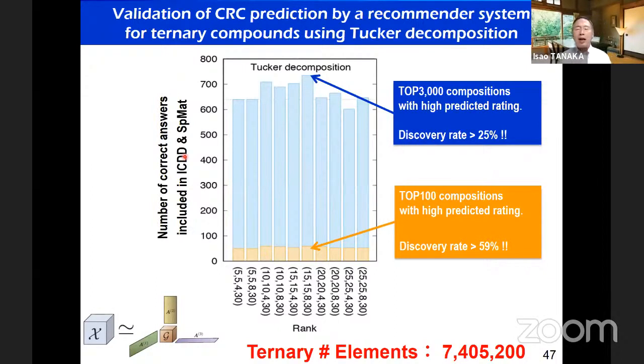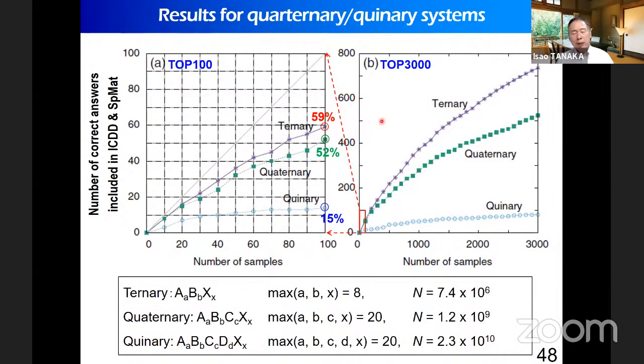This is another astonishing result, because remember that we didn't use any descriptors, any first principles results, no prior knowledge, just rearranging the elements in the tensor to find a discovery rate of close to 59%. The discovery rate is even 25% for the top 3,000 compositions. It is similar for the quaternary system. But for the quinary system, the success rate is lower by 1/4. But we know the reason.